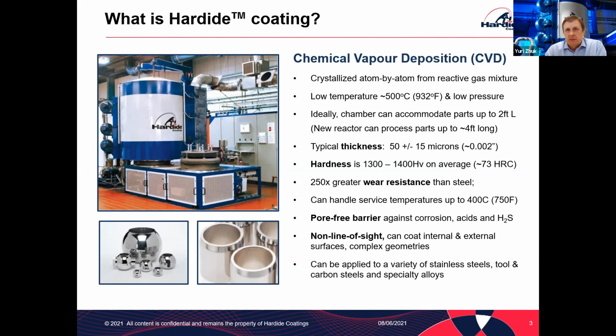Typically, we coat parts about 2 foot long, but we recently installed a larger reactor, which allows us to coat up to 4 foot long components. Typical thickness of the coating is about 50 microns, so 2 thou, and hardness on the level of about 73 Rockwell C. So it's about 1300, 1400 Vickers. So it's pretty hard.